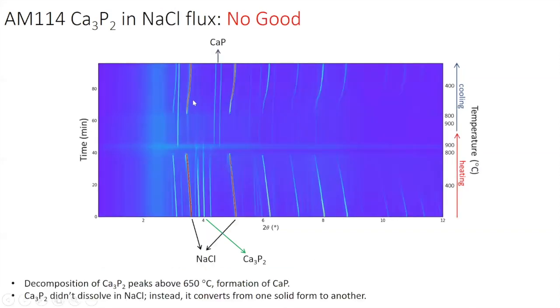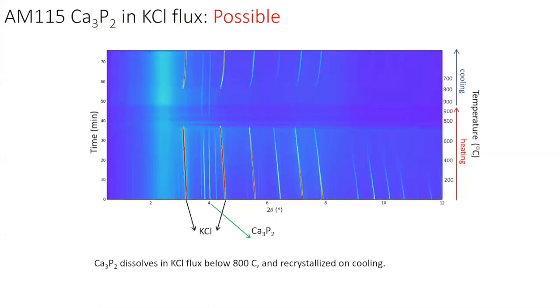And if we would cool down again, you can see that those peaks intensify and the flux peaks come back. This means that the flux solidified. So we would say this is very promising as a flux.